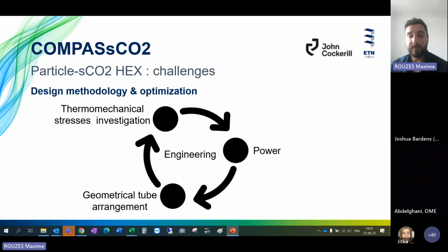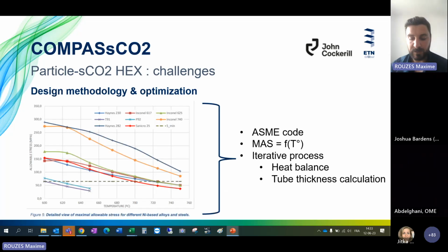So basically here, very quickly, in the engineering we will have to make compromises between the three different items here: the total power with the heat balance, the arrangement that we want with the tubes, and all the selection of the materials. And obviously, as the first rows at the top of the heat exchanger will be impacted by solid particles at 900 degrees and have sCO2 flowing inside at 700 degrees C, we can imagine that the stresses will be very high. So we need to investigate this aspect with thermomechanical stress calculations here. There's no magical recipe. It is all a matter of compromise between cost and all the design criteria that we have here.